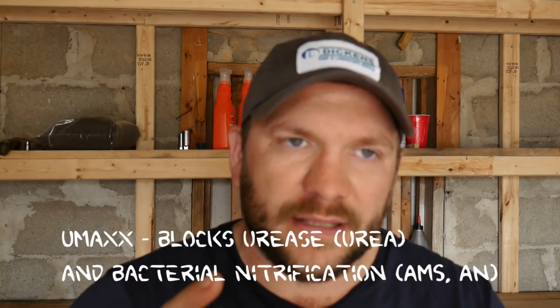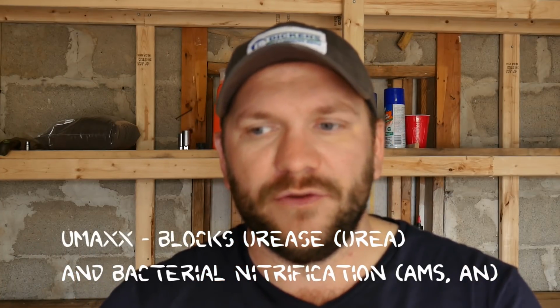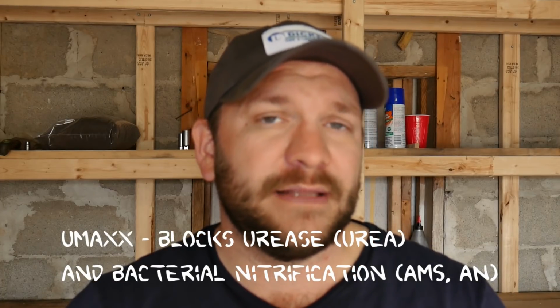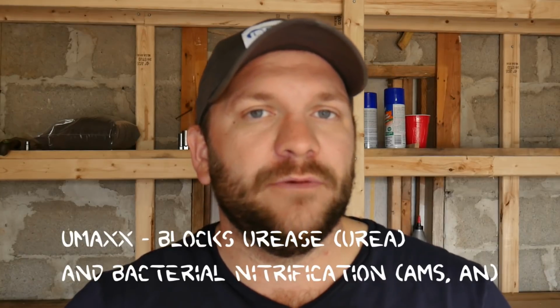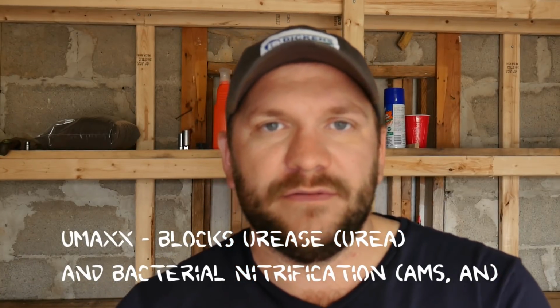Whereas with the N-butyl thiophosphoric triamide, the Umax variety, what happens is, yes, it blocks the urease enzyme, but it also blocks soil bacteria from turning ammonia into nitrate. So it will work on something like ammonium sulfate to a degree. Again, this is one of those products where Umax would work well with ammonium sulfate. It's going to allow the ammonium sulfate to immediately release in terms of the ammonia gas that is produced. However, as that breaks down into nitrate, it will be slowed by that nitrification inhibitor.